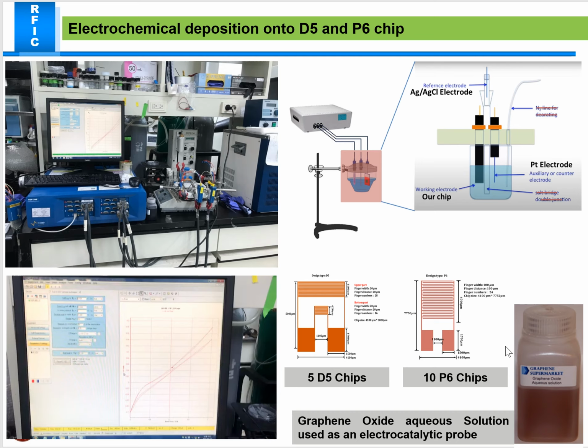Previously I did 5 D5 chips and 10 P6 chips, and I'm pretty sure the P6 is much better than the D5 because the deposition of the graphene is higher than on the D5. The reason is that in between the fingers there is a large surface area, and also the whole chip has a large surface area. So this is the positive factor of the P6 chip. This week on Friday I will go with the P6 chip and use it for the electrochemical deposition instead of D5. And obviously I have to use a graphene oxide aqueous solution as an electrocatalytic probe.